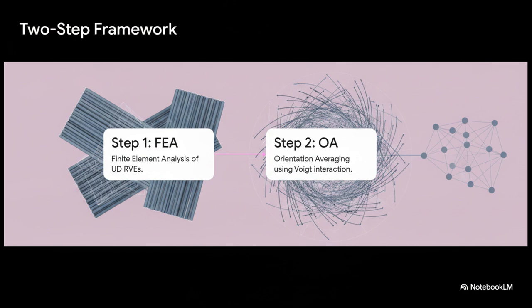Step 1 is performing finite element analysis on unidirectional representative volume elements, or UDRVs. Basically, you're simulating a tiny microscopic block where all the fibers are perfectly aligned, pointing in the exact same direction. Then, Step 2 takes those clean results and applies orientation averaging using a Voigt interaction assumption. In plain English, that's calculating how properties physically blend when those perfectly aligned fibers are realistically scattered and rotated in the final material. This two-step process is honestly kind of genius because it completely unchains the model from the usual limitations of arbitrary aspect ratios or high volume fractions.